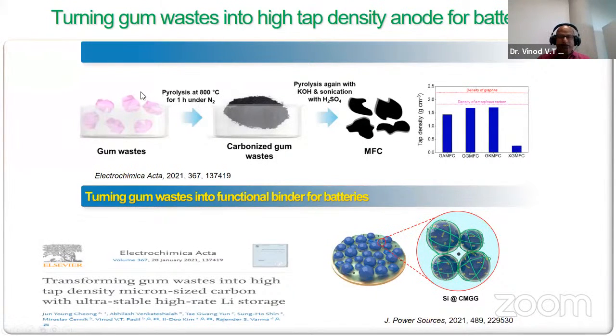When you collect this gum waste and use pyrolysis at 800 degrees Celsius for 1 hour under a nitrogen atmosphere, we can make a carbonized gum. These carbonized gums, with some treatment with potassium hydroxide and sonication under sulfuric acid, can make carbon fibers.